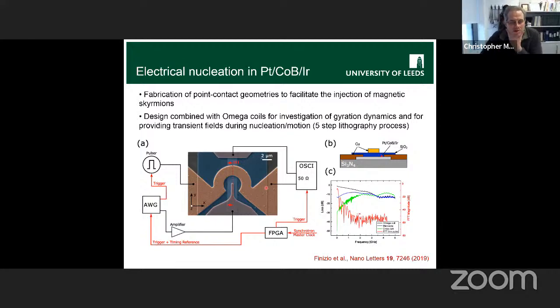Okay. So this is our nucleator device. And again, there's some false color here to help you understand it. The magnetic wire is this rectangle in the middle. That's a 2 micron wide wire, and it's made of the same kind of multilayer that we've seen already. And it's got copper electrical contacts at either end. And one of those is shaped into this sort of finger that you can see here. And there's a radius of curvature at the tip that's about 250 nanometers. So if we send a pulse of current along this wire and inject it from this finger, then there's going to be a very high current density at the tip of the finger that spreads out into the wire.